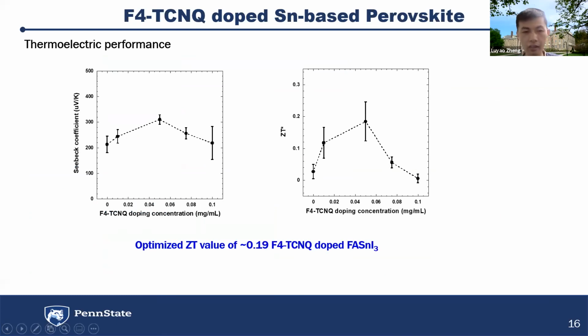So after that, we try to measure the Seebeck coefficient of the thin film, doped or intrinsic, and we calculate the ZT value. We can obtain a ZT value of 0.19 from this doped thin film at room temperature. This is pretty good compared to the previous literature reports, some only about 0.15 at 300 Kelvin. So we can achieve an even higher ZT value at room temperature.